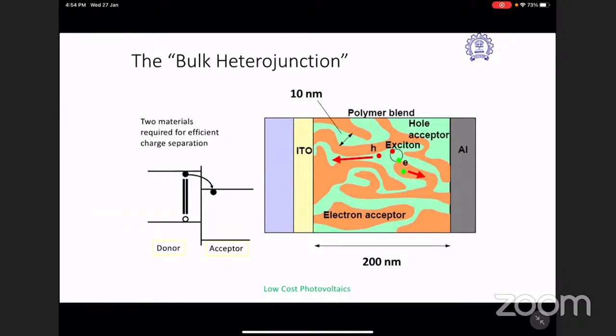Hole will stay on the bottom level of the donor, and electron will stay on the top level of the acceptor, and you will be having an electron-hole pair which will be at the interface of this donor-acceptor system. So the two materials are required for efficient charge separation. You need a kind of molecular knife to break that exciton. So when you shine the light on the donor, your exciton will diffuse and reach this interface, and there is a lower energy state available, so it will get transferred.